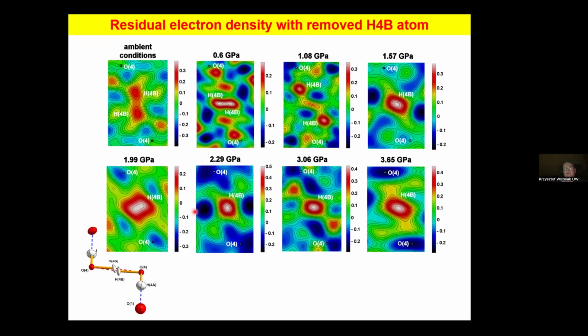When we refine this up to the very end, we can remove this H4B hydrogen, and keep refining further in order to see residual electron density in this hydrogen bonding. And here you see evolution of this position of residual electron density, and this hydrogen bonding is disordered, and degree of this disorder keeps changing with increasing pressure. Then it starts localizing at the center, and very strong symmetric hydrogen bond is created.